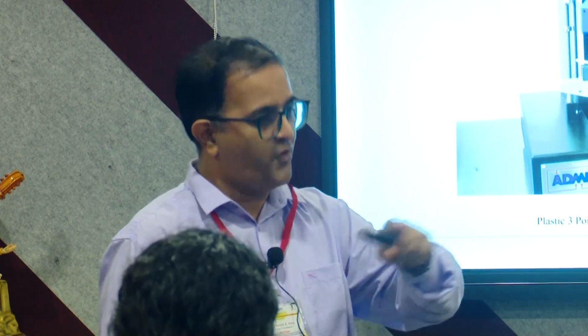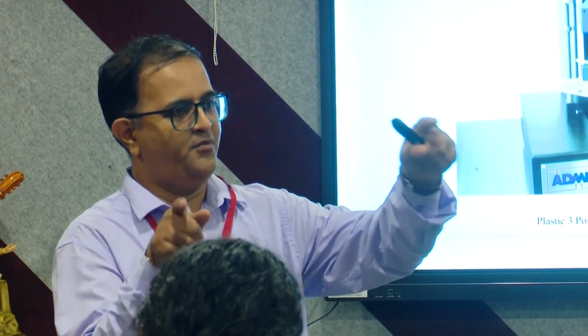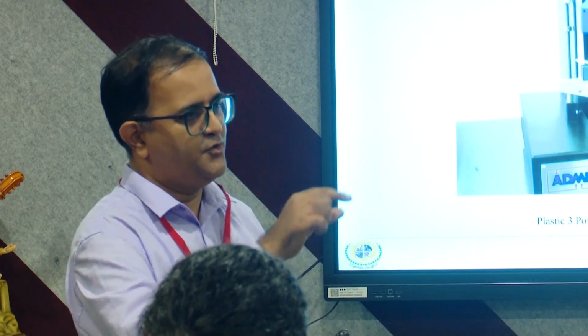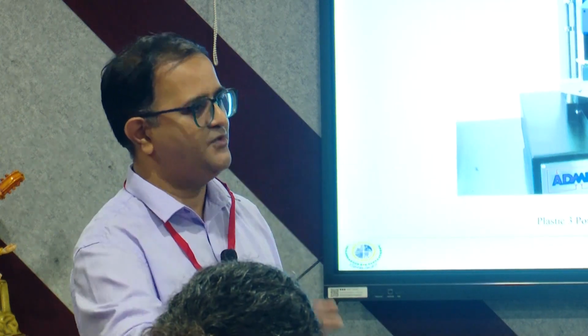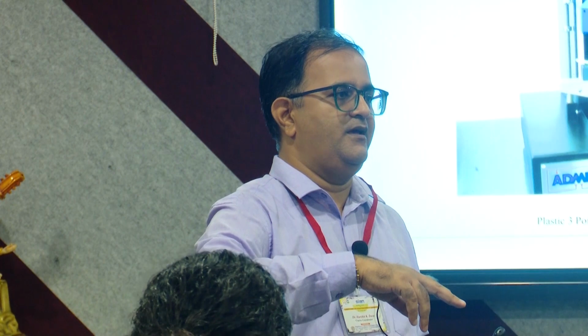Yes, yes. Maybe in that particular case where Himanshu worked, he took 5 to 6 repetitions of all the samples, and those 6 were not taken from a single part. Once you make a plate, you cut the tensile part, impact, and flexure from it. So one plate will give you one or say two samples for each. Had I taken all 6 impact samples from the same plate, maybe I would not have got any difference.